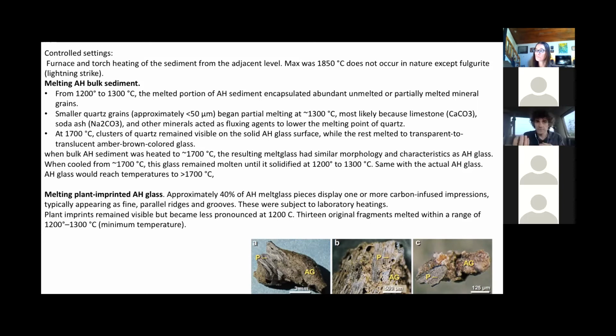The glass which was forming had a brown color, and it was very similar to the actual Abu Hureyra glass. During the cooling, we saw a solidification of the sediment that we melted at 1300. When we did the same thing with the glass, we remelted the Abu Hureyra glass that we found and watched when it becomes solid. It was the same temperature, so this is probably happening: the material is the same.